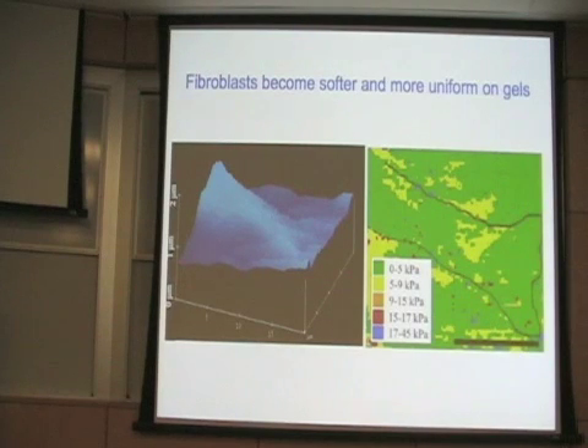The cell is relatively uniformly stiff in one of these protrusive areas. The protrusions are also much more blunted. But the cell is approximately as stiff as the gel outside it. And that's not a coincidence, at least for this cell type.